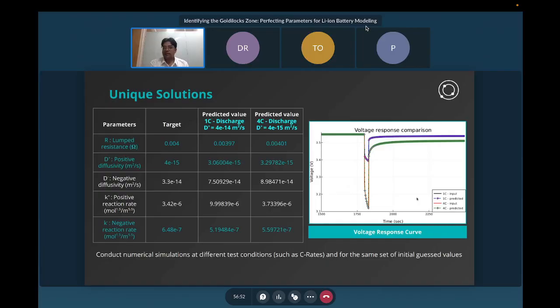Then we started matching which sets from these two experiments match closely. And we could find that for an initial guess of D' equal to 4e-14 for 1C discharge and 4e-15 for 4C discharge, they both led to parameter estimates which were close enough. And they were also close enough to the target value. Basically, what we established is that if we repeat these experiments at different C rates and do the initial guess variation exercise, we have a possibility of still getting to the unique solutions, even if we know that some of these parameters might be insensitive, and so cannot be unique sets to capture that voltage profile.